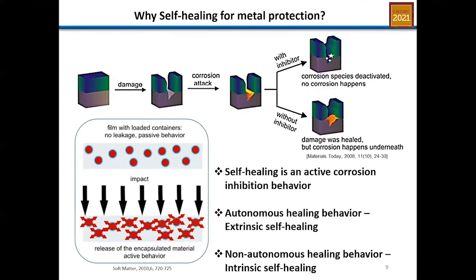So why do we need self-healing actually? When a coating is damaged and corrosion attacks the underlying metal, if you have inhibitors embedded in it in such a way that they are not deactivated before time, there is a possibility that the corrosion species can be deactivated in the presence of these inhibitors that are leached out on time. But without the inhibitors, the damage may be healed on the surface depending on the nature of the resin or the matrix that is being used, but then corrosion has occurred underneath, and this actually results in a lot of catastrophic failures.